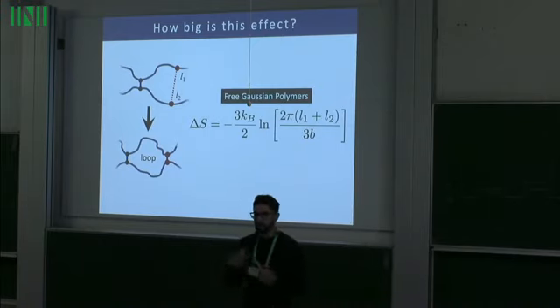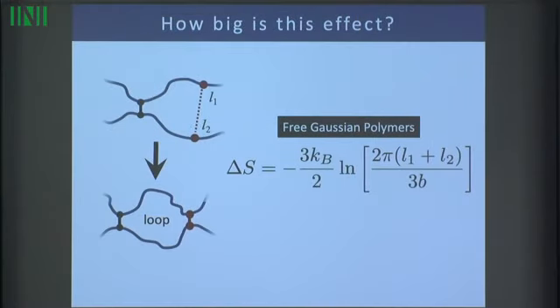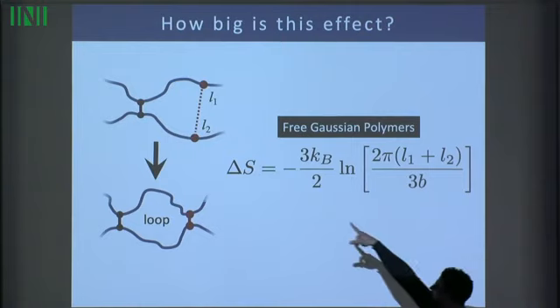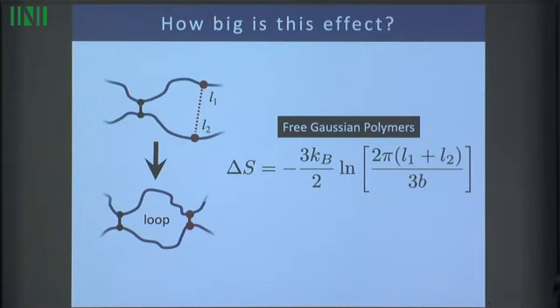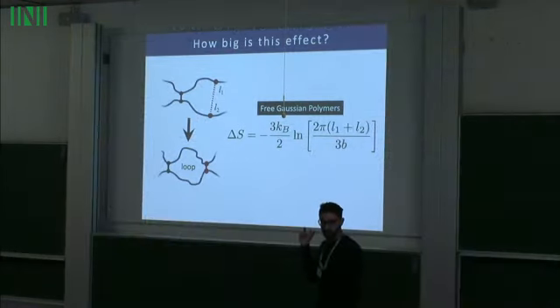You can quantify it through a few different ways. The easiest one to start with is the Gaussian polymer chain model. So you just treat these polymers as two Gaussian polymers extending from a point in space. And you can back out this equation, and this is just a back-of-the-envelope calculation. It's actually the cost of the entropy for forming a loop between the two polymers, as shown going, oh, this laser doesn't work, as going from the top to the bottom picture. And this effect is not enormous in this case, because it depends logarithmically on the contour length of the loop size, okay? So I have to go actually quite far out to get a significant entropy penalty. So it's there, but it's not enormous in this case.